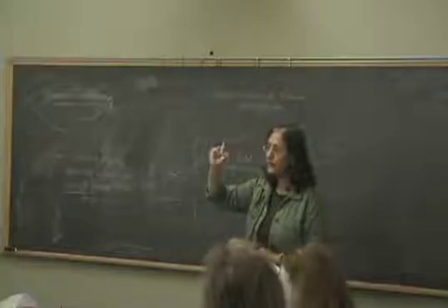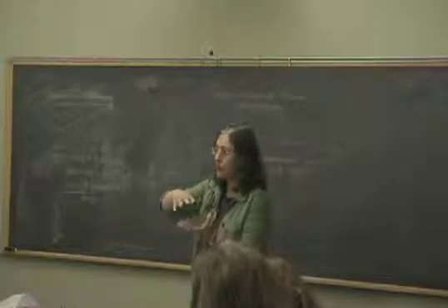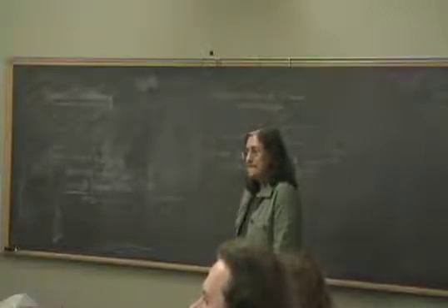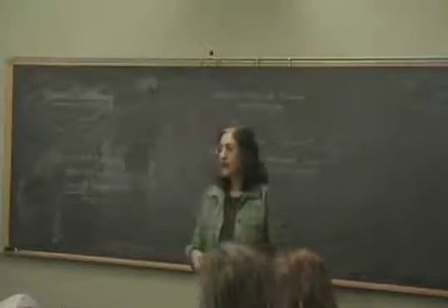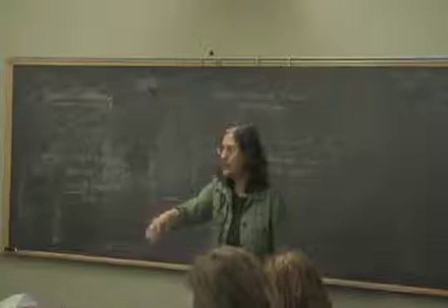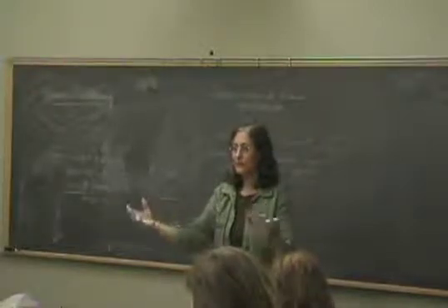But with AC, you get an even more sensitive response because now you have an electric field at some frequency. You can even make it resonant with, let's say you are probing another object. You can even make it resonant with the plasma frequency of that object, and you will get a huge absorption. Right. So I guess I don't understand how it would work in the DC case. No, you don't want to use this in the DC case. So think of our metal sphere in some dielectric. You could bring the tip and excite a plasma mode on one dot, and then nothing in the dielectric, and then move it to another dot, and so on. So the idea would be to do it in an inhomogeneous situation where you're mapping out the different metallic puddles or different molecules.